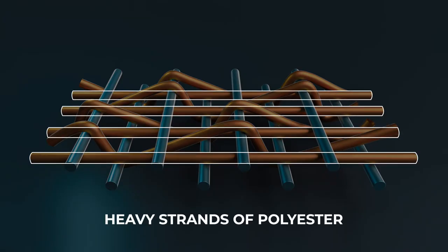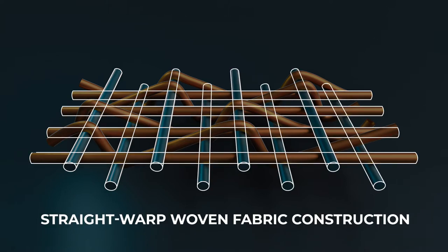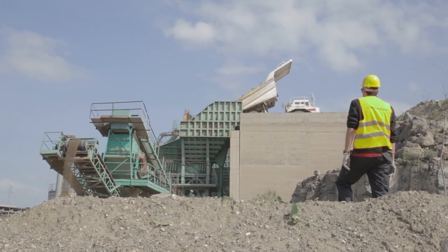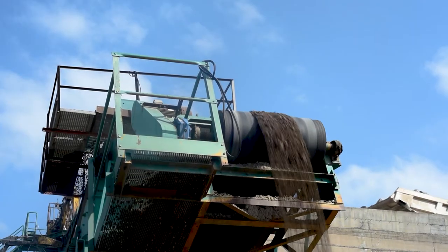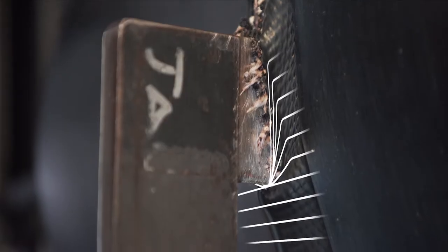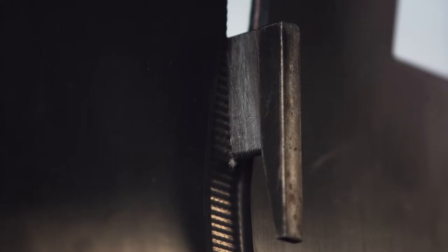A primary layer of heavy strands of polyester yarns running lengthwise are placed between two parallel planes of extremely strong crosswise nylon yarns. The strands are completely straight in both directions and not interlocked as in a conventional belt carcass. This enables the weft to float free from the warp, allowing it to effectively act as a built-in ripstop breaker. When a trapped object is being pulled through the belt crosswise, strands of the USFLEX stretch and gather together into a bundle that can become strong enough to bring the belt to a stop, thereby limiting the length of the damage.